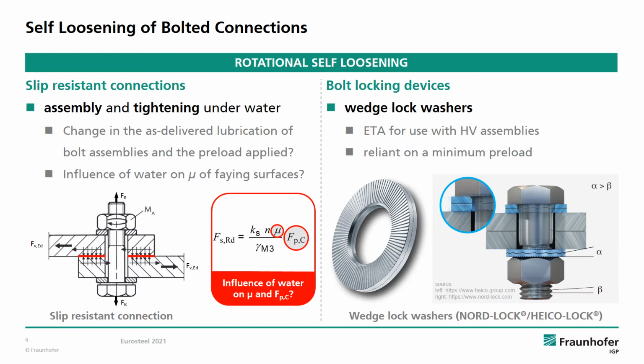But considering the presence of water during assembly, the two key aspects of design might actually be altered when executing, or respectively assembling and tightening, the connections on site. The maintenance of the as-delivered lubrication is crucial for high-strength structural bolting assemblies for achieving the nominal minimum bolt preload with the tightening methods listed in EN 1090. Typically, HV nuts are lubricated with molybdenum disulfide, which is actually well known to reduce its friction properties in contact with water. Also, the slip factor might be influenced by the presence of water in between faying surfaces as well.